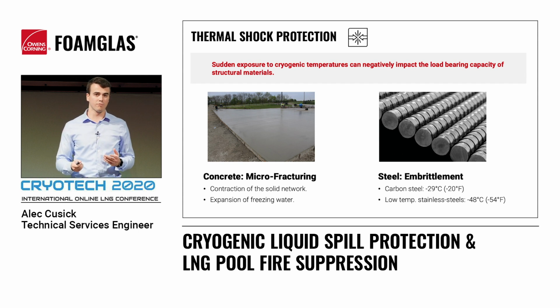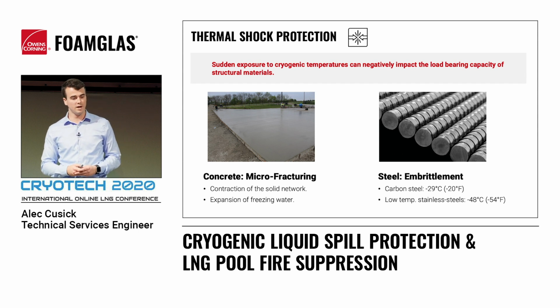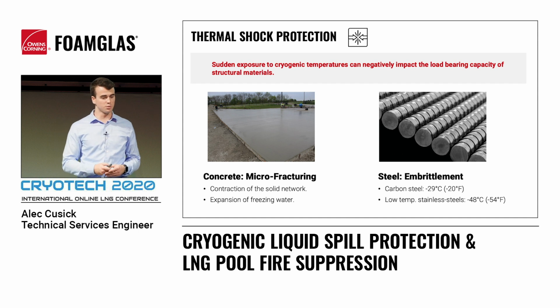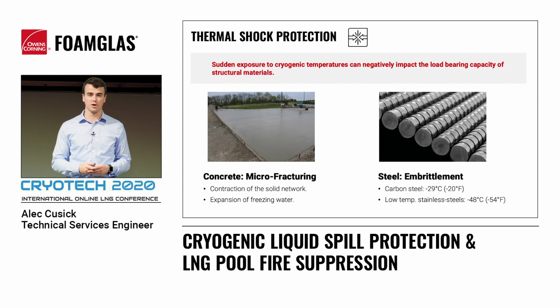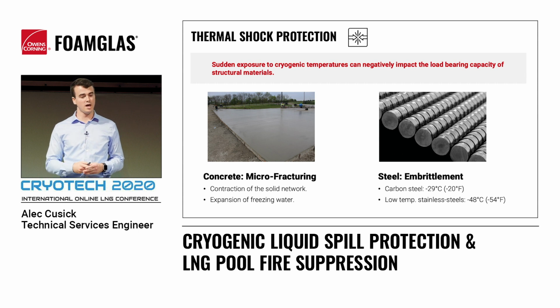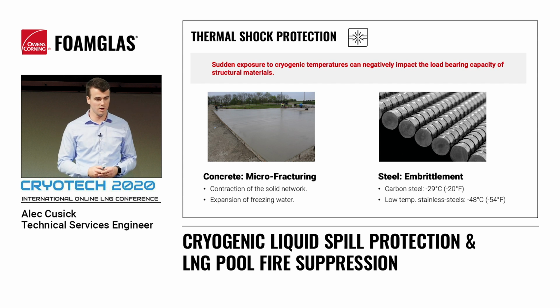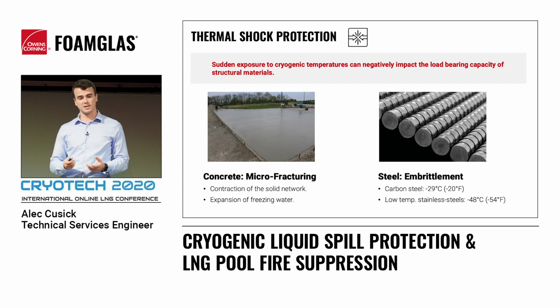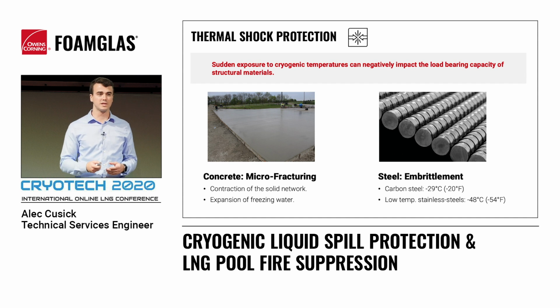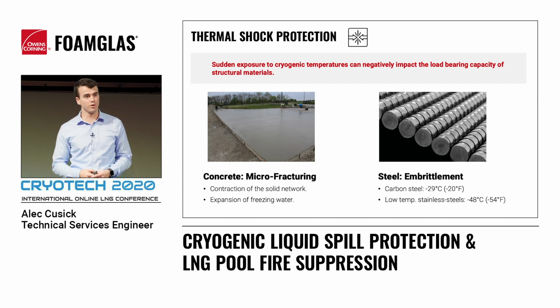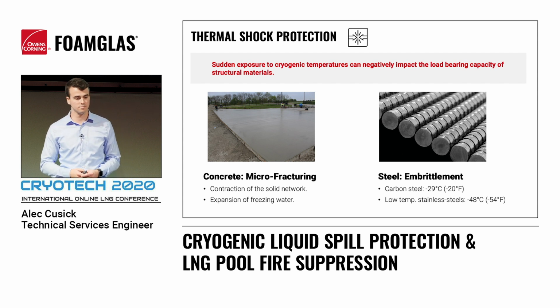When rapidly exposed to subfreezing temperatures, concrete may undergo multiple processes that can cause microfractures to occur. This can include contraction of the solid network, as well as expansion of water freezing within the concrete structure. Carbon steel, on the other hand, may begin to become brittle and fracture at temperatures of around negative 29 degrees Celsius. Certain grades of low-temperature stainless steel may be tolerant to as low temperatures as negative 48 degrees Celsius. However, it should be noted that these special grades of stainless steel can prove to be quite expensive. It can really expand the cost of a construction of a containment pit should they be required on site.